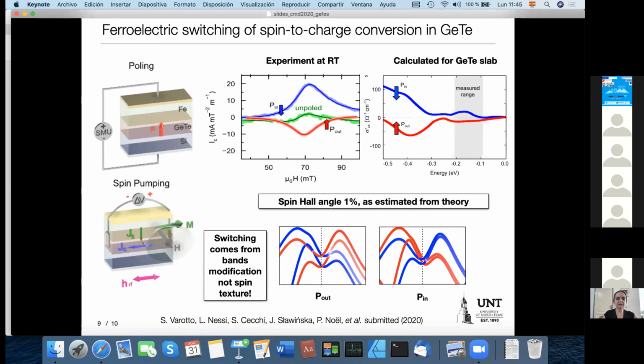So here on the left, I present one experimental setup and just two views to facilitate the explanations. Here in the upper panel, I show how it actually looks. So germanium telluride is embedded between iron and silicon. We have the electric polarization perpendicular to the sample, and we can change the ferroelectric state. Then it's still the same interface,